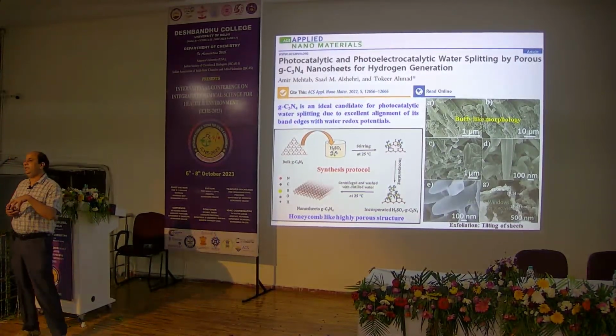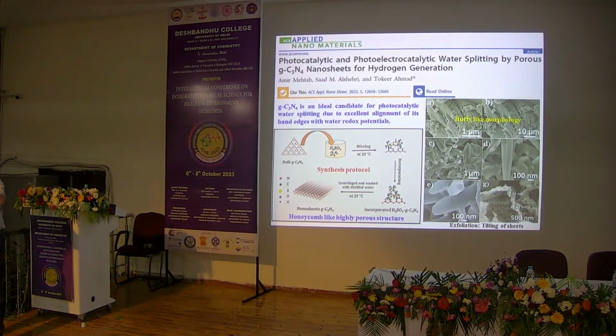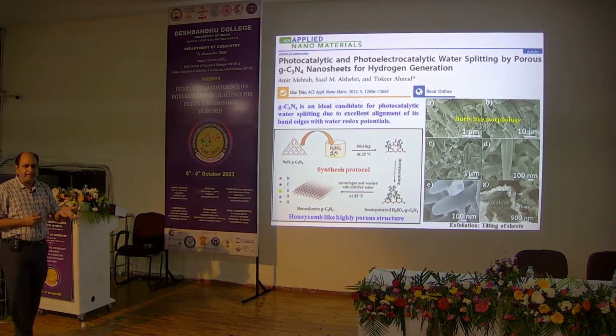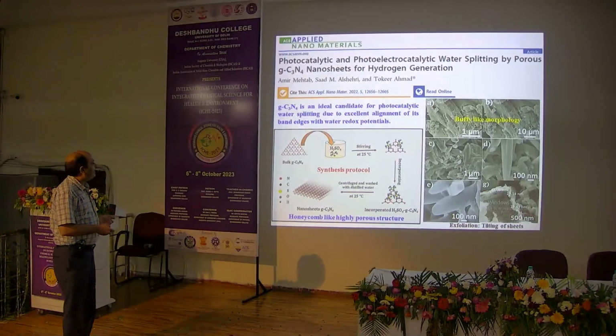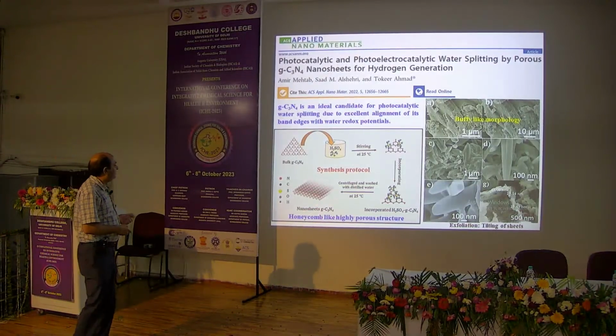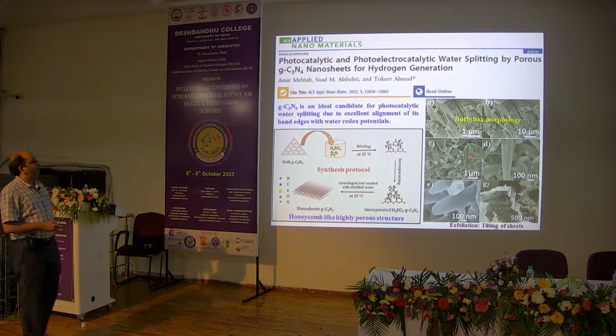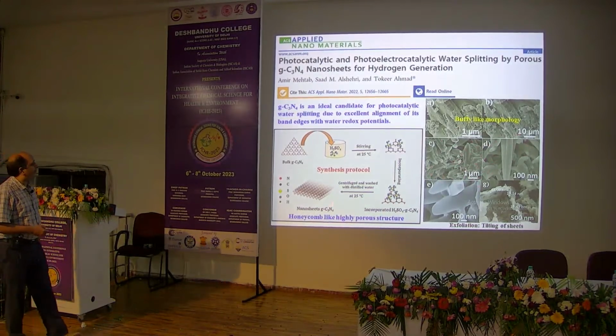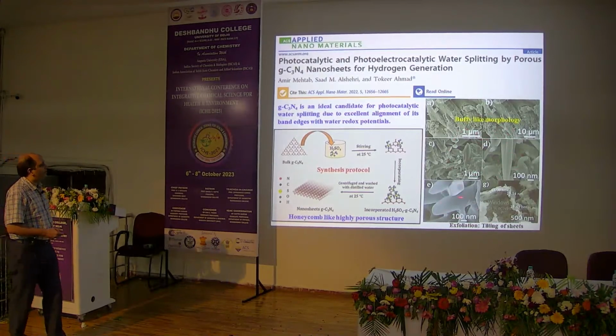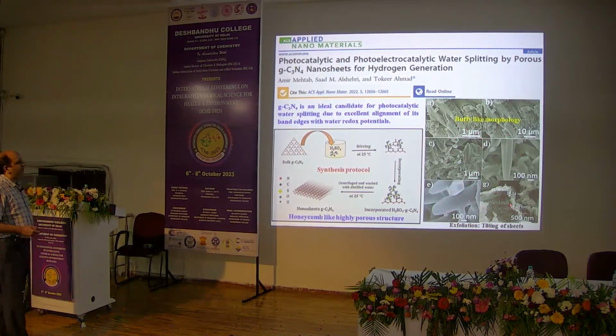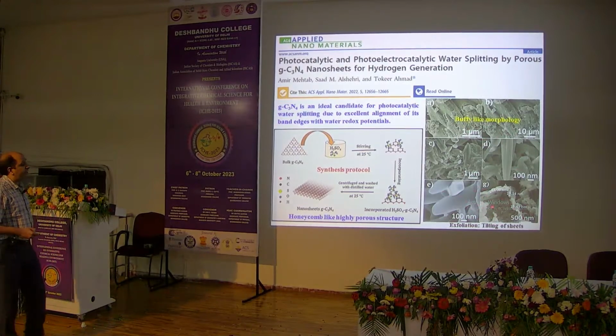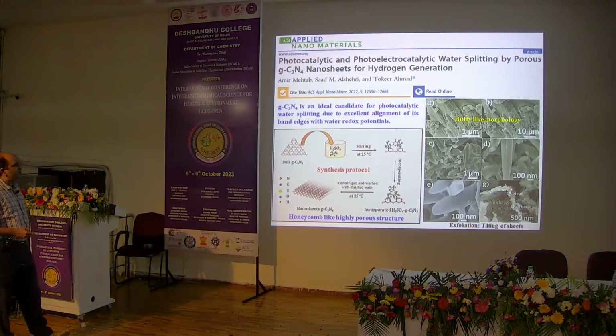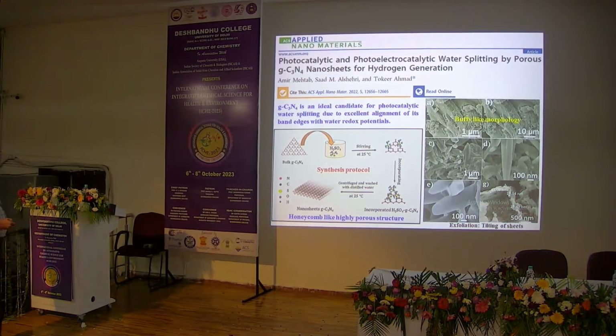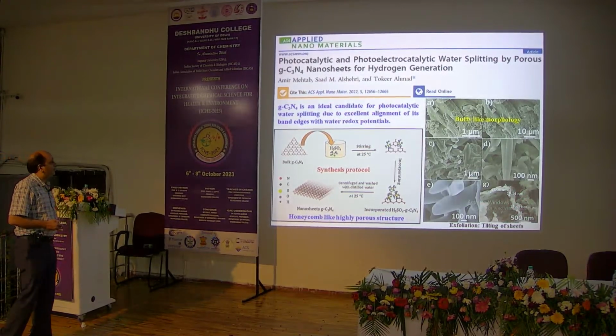And if you exfoliate this bulk graphitic carbon nitride in sulfuric acid or HCl, you will have very beautiful nanosheets of graphitic carbon nitride, and these are the electron microscopic images of these graphitic carbon nitride nanosheets. These have a fluffy-like morphology, and if you have an understanding of HRTEM and SEM, then you could see the tilting of sheets during exfoliation of the graphitic carbon nitride.